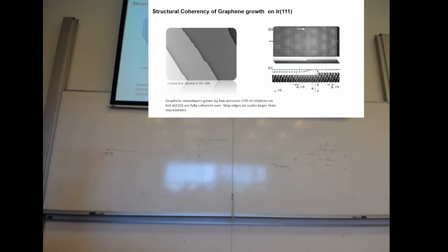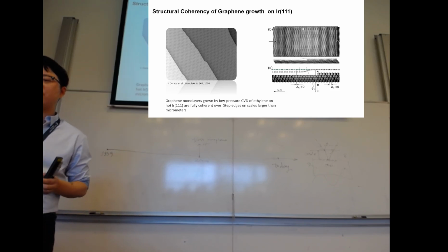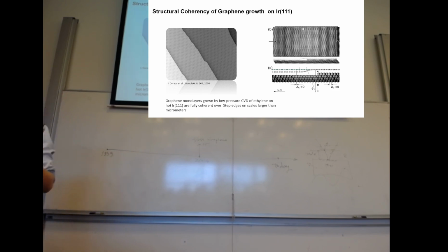Okay. So there are also experiments in 2008, very rapidly after this famous Science paper. It's like 4 years later, people had developed a lot of different facilities to grow graphene, especially on iridium, gold, and things like that. So people found that it's actually really easy to grow graphene. You just decompose some methane or any kind of carbon precursors, and the carbon will recombine by sp2 bonding and form this honeycomb lattice of 2D, down to monolayer.